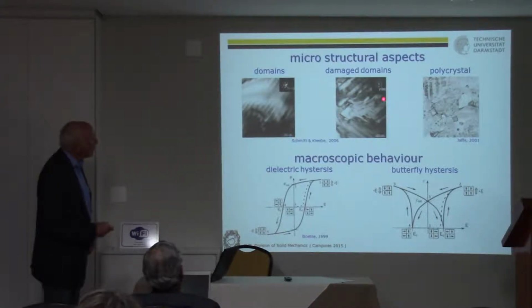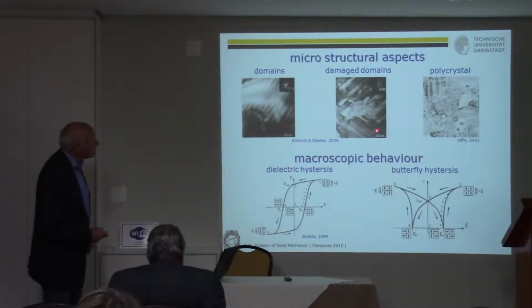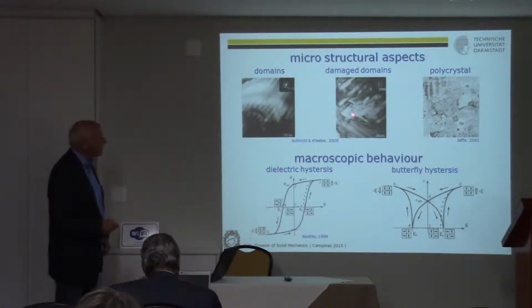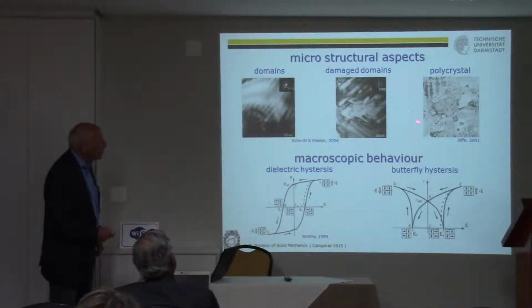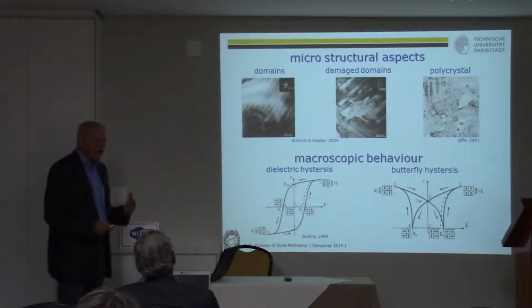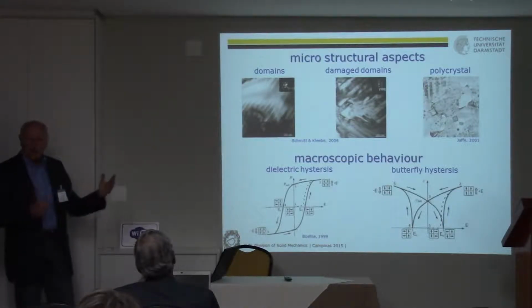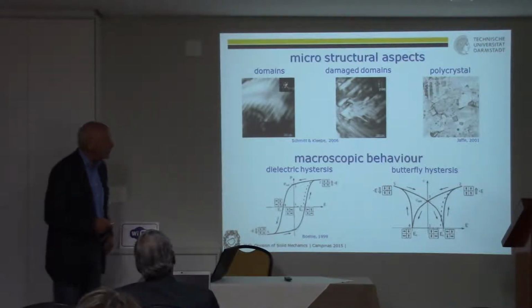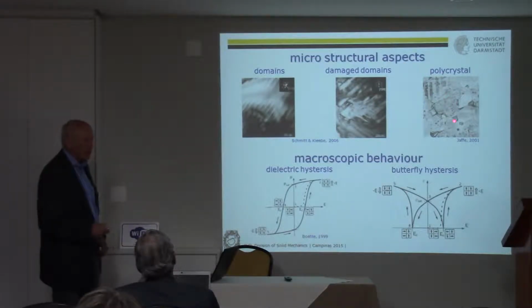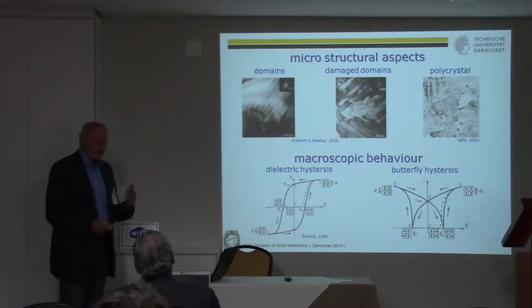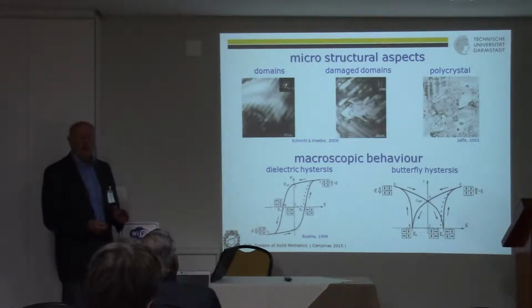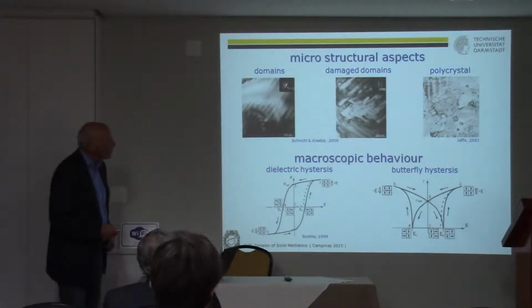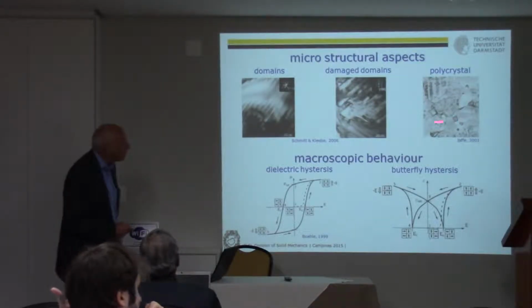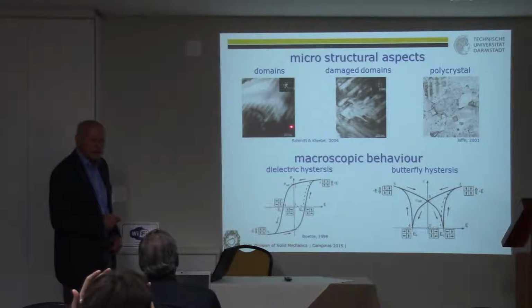Then here on, say, mesoscopic scale, you see damaged domains here, on account of a crack. Yeah, and if you look at the real material as it is used in devices like this fuel injection system, then it's a polycrystal. Yeah. And it's a hard, stiff polycrystal like a ceramics, yeah? And within each grain, you find this structure here of domains, yeah?